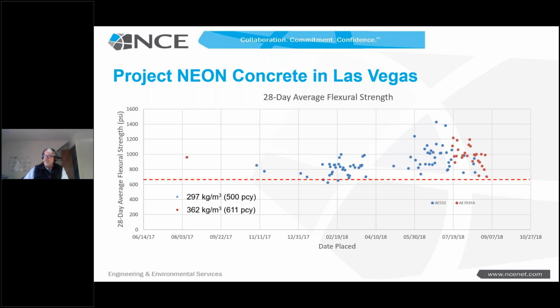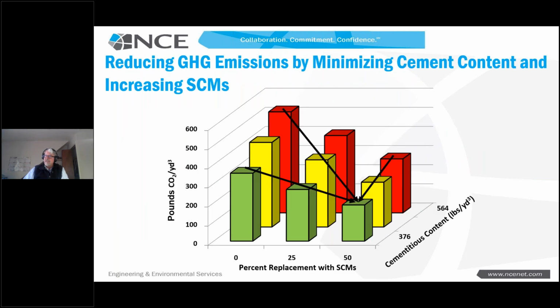And so this is a clear indication that real concrete being placed on grade in multiple places around the country are being placed with very low cementitious content. And so the takeaway is, if we increase the amount of SCM or other additives to replace clinker, like an LC3 system or a blended cement system or blending at the concrete plant, and we use optimized aggregate grading to reduce our cementitious content, we can dramatically reduce the amount of greenhouse gases associated with our concrete. This is a very, very important point.